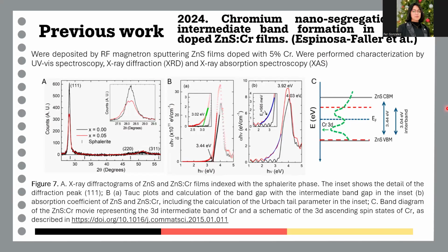Two important implications for the production of photocatalytic hydrogen were studied. First, that the nanosegregation of the dopant can modify the intermediate state density and the relationship between the absorption of the photon in the intermediate band within the band gap and the recombination. And second, the structural stability of the system, especially in the presence of the electrolyte, this being a critical parameter to guarantee the generation of hydrogen.